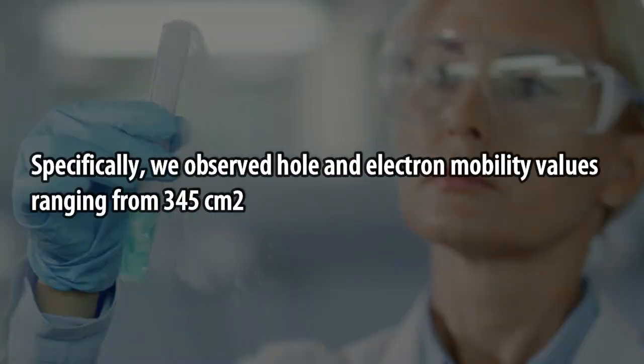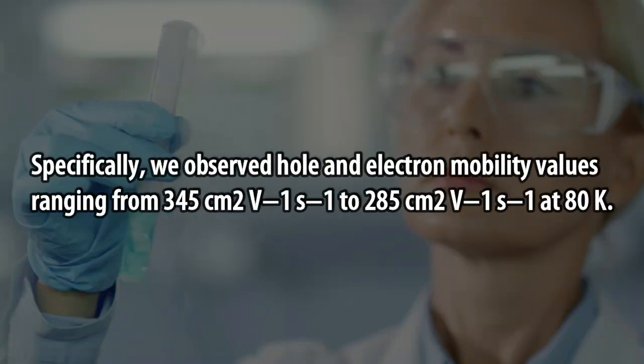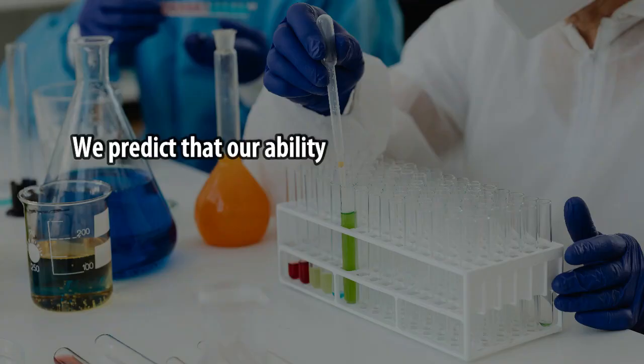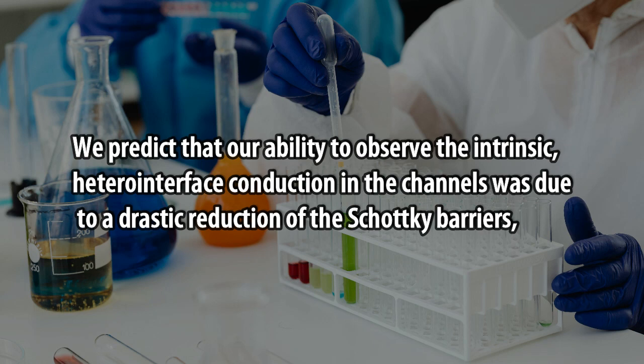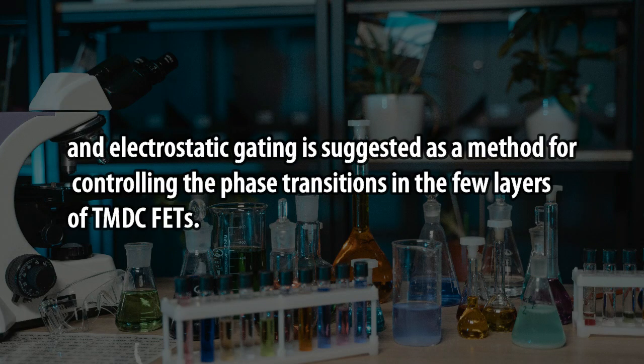Specifically, we observed hole and electron mobility values ranging from 345 cm² V⁻¹ s⁻¹ to 285 cm² V⁻¹ s⁻¹ at 80 K. We predict that our ability to observe the intrinsic heterointerface conduction in the channels was due to a drastic reduction of the Schottky barriers, and electrostatic gating is suggested as a method for controlling the phase transitions in the few layers of TMDC FETs.